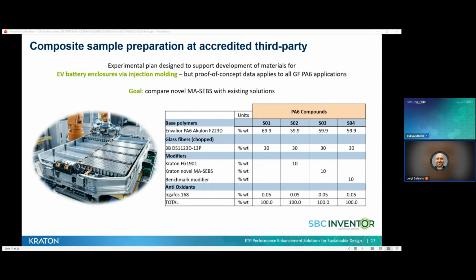We chose as a reference formulation a common polyamide 6 material filled with 30% glass fiber suitable for injection molding application. This material was then modified with the go-to malleated elastomer Kraton FG1901, as well as with our novel malleated SEBS structure and an external malleated polymer as a benchmark. Just for your reference, if you worked with us previously, you know that we specialize in relatively soft materials, and our lab equipment is specifically selected to handle them. Therefore, to produce these hard and abrasive compounds, we prefer to cooperate with an accredited third-party lab in Germany who specializes in making glass fiber-filled compounds.